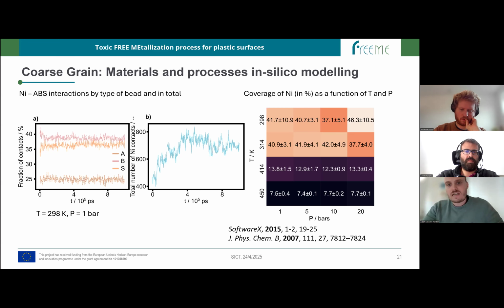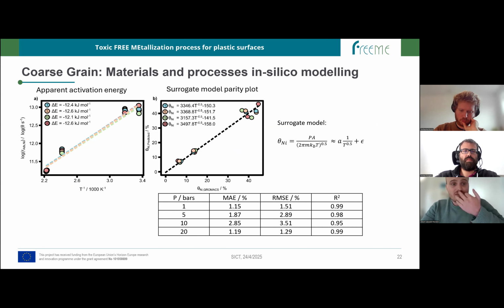We took these temperature and pressure ranges because first we wanted to investigate what happens below the glass transition temperature of the monomer and above that temperature value. What we can see is that the coverage of nickel decreases with temperature, while we are not very sure to find any kind of relationship or trend with pressure, which I think also makes sense. And finally, from these results, the other thing that we can do is to extract some kind of